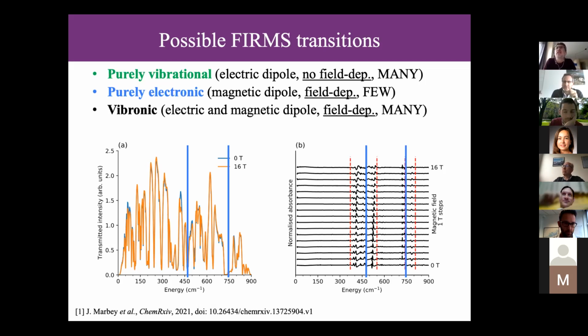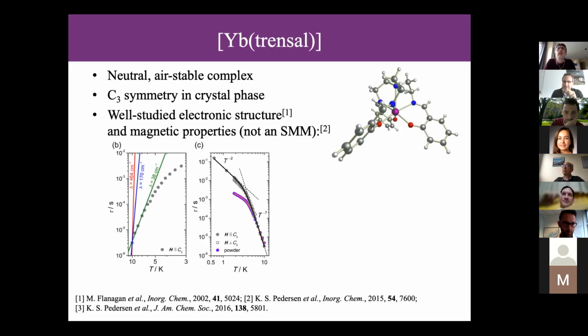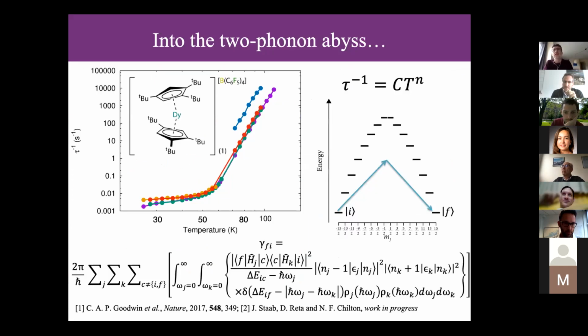Nick, I would like to come back on your 2-phonon process. If I understand well, it means that you do not need the overlap between the electronic transition and the vibrational one. Correct. So it means that every time you have this kind of 2-phonon process, you have a shortcut and you have a relaxation that is fastened.